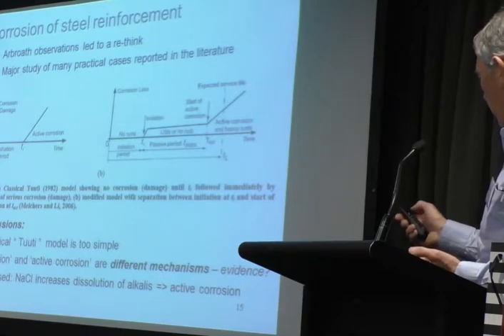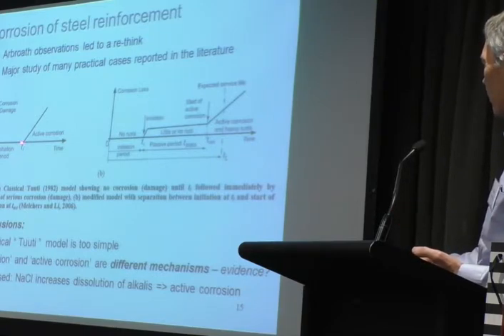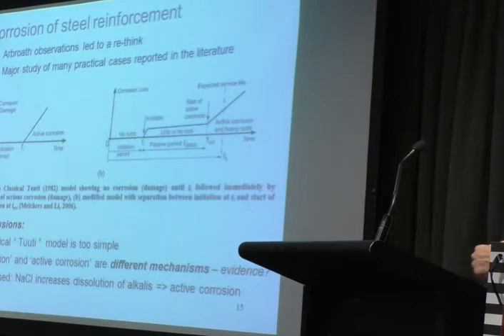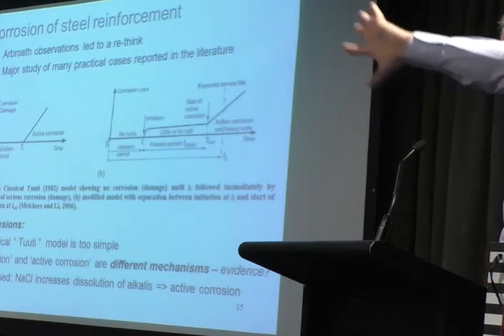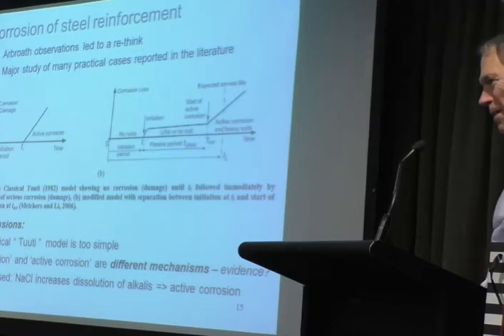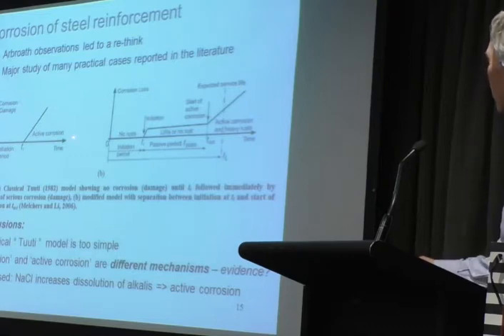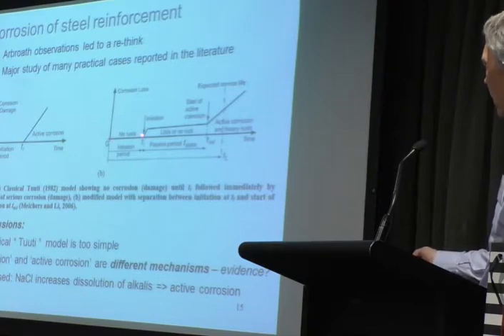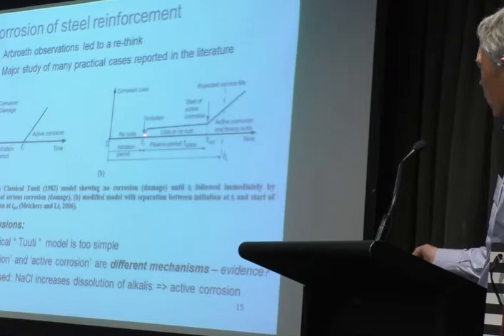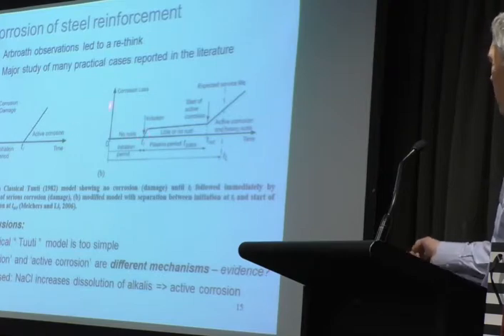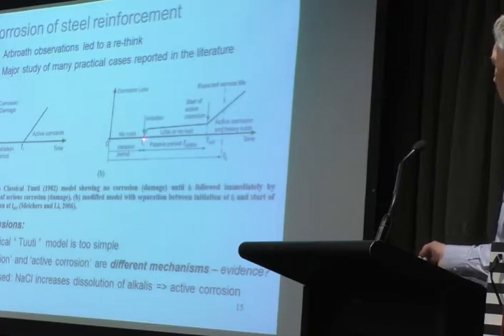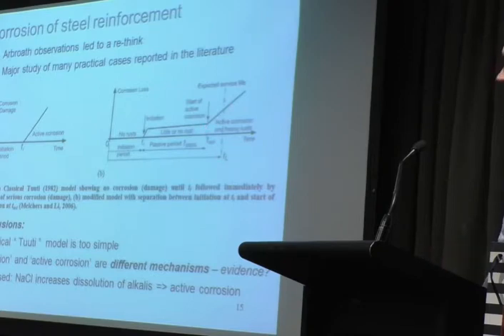And the model you've heard a lot about already is the so-called Tuutti model. That goes initiation time and then corrosion starts. And the more we looked at lots of examples, which I'm cutting through a whole lot of work here, months and months and months of literature survey that I'll come back to in a minute, we decided in the end there's something funny about the way it works. We get initiation, small amount of corrosion will occur. This is corrosion loss, if you like, or damage, whatever. Doesn't matter. No, not damage, corrosion loss. Damage is different. And then nothing much happens. And then only later on do you get this active corrosion.